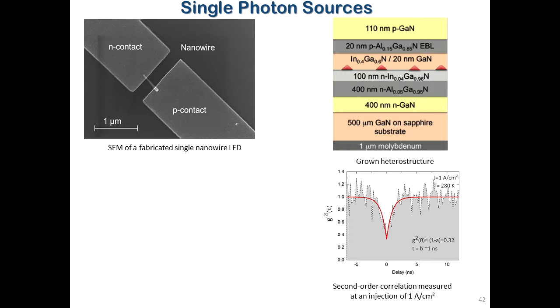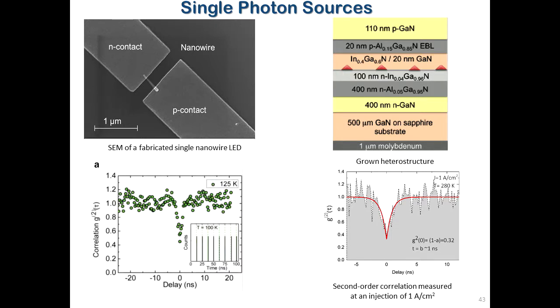And of course, with that, you see this second order correlation. What this is saying is that the photons coming out go to two photodetectors through a 50-50 beam splitter, and we measure the delay of the arrival time of the photons and build a histogram. At zero delay, if the count is zero, then you know that you don't have two photons coming at the same time. And so here you see it.